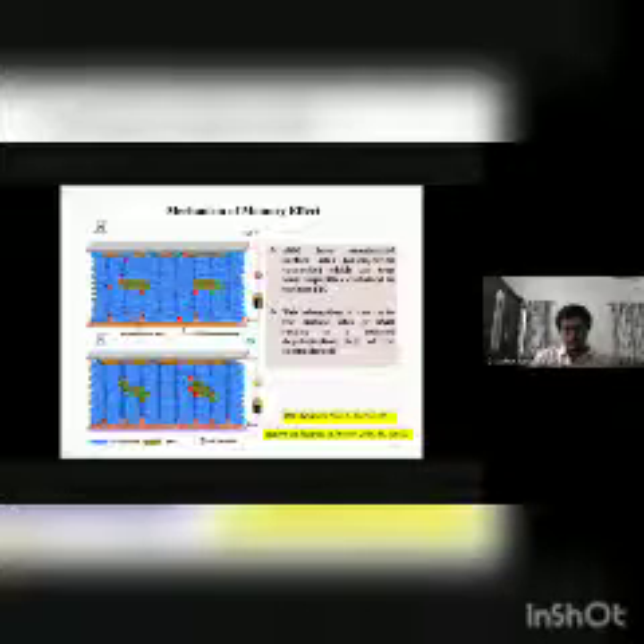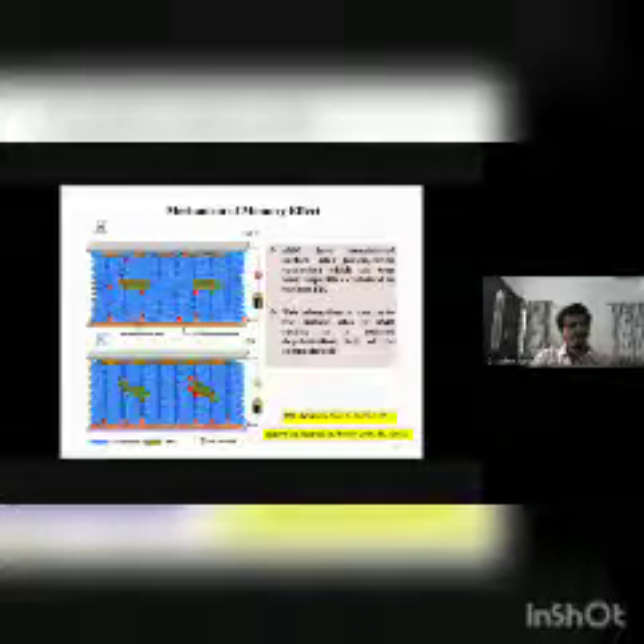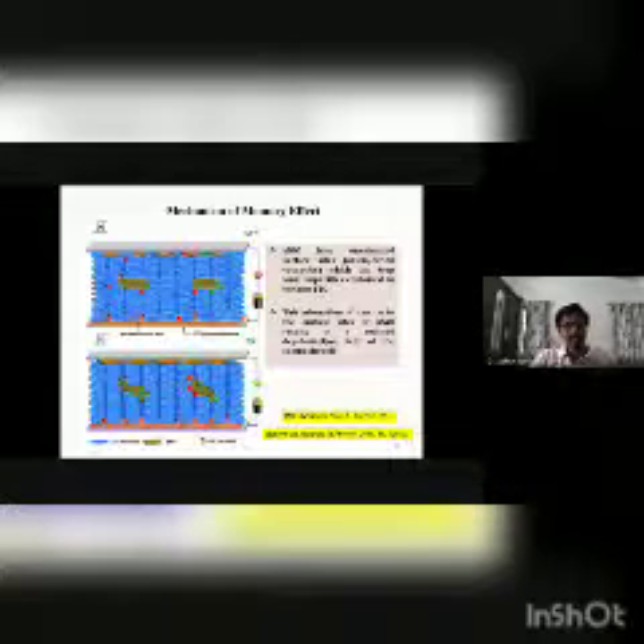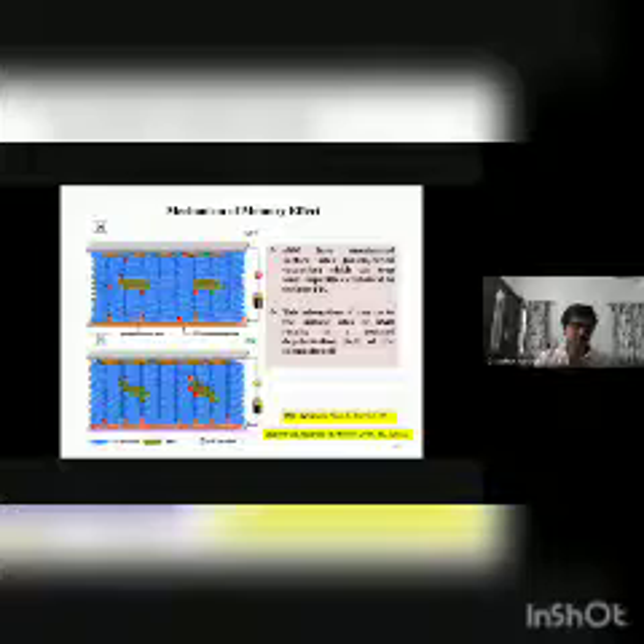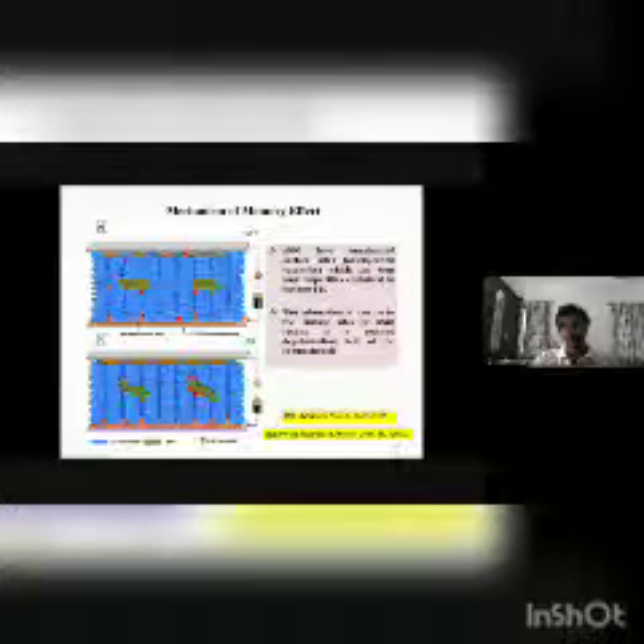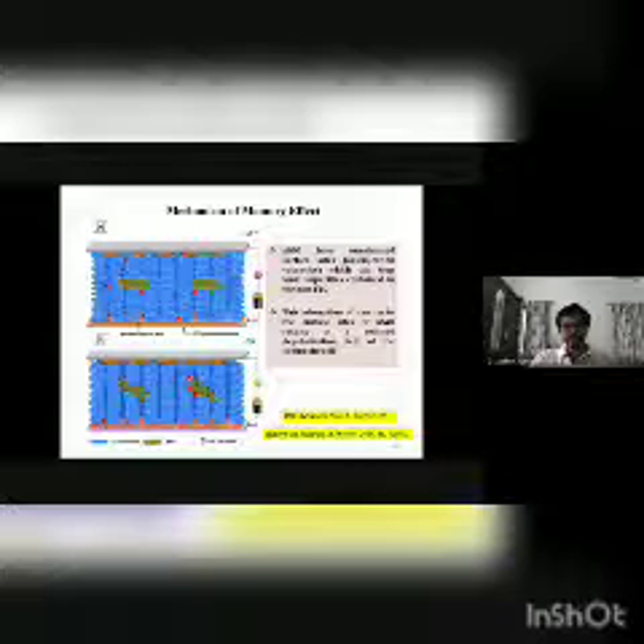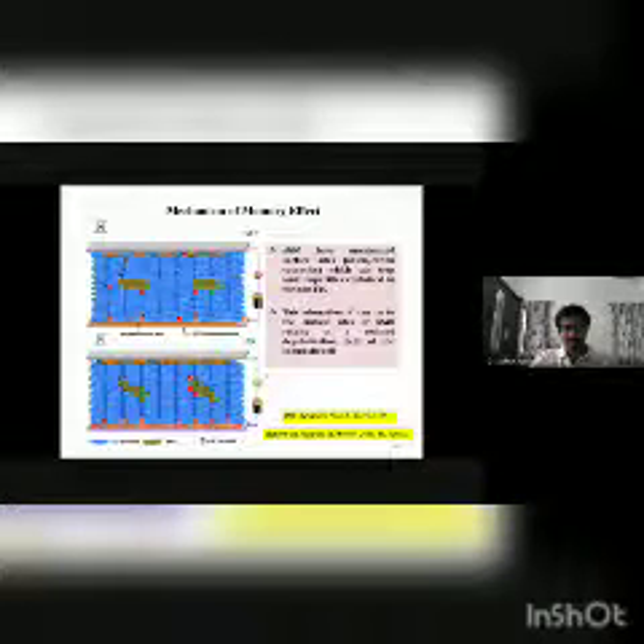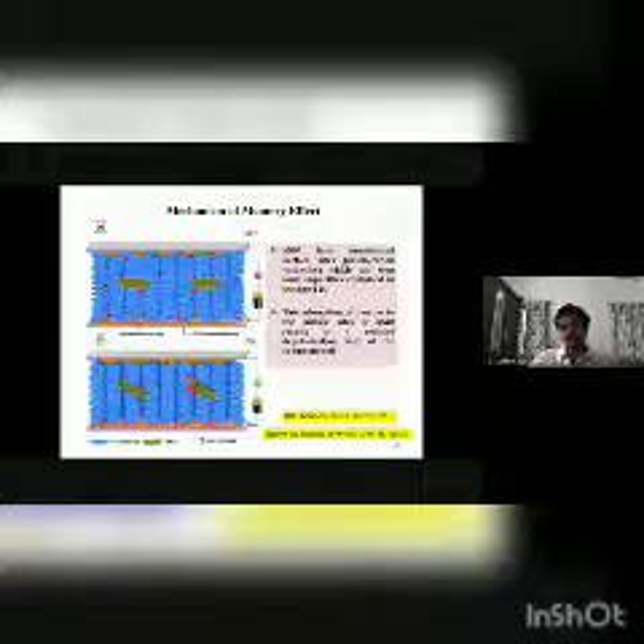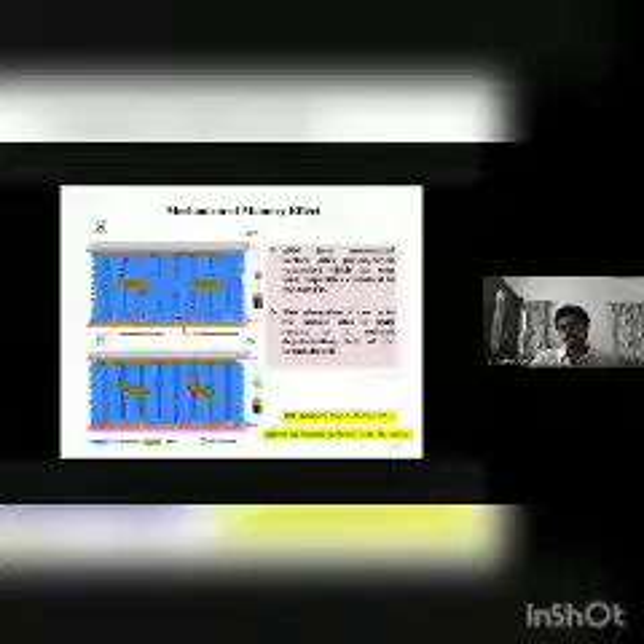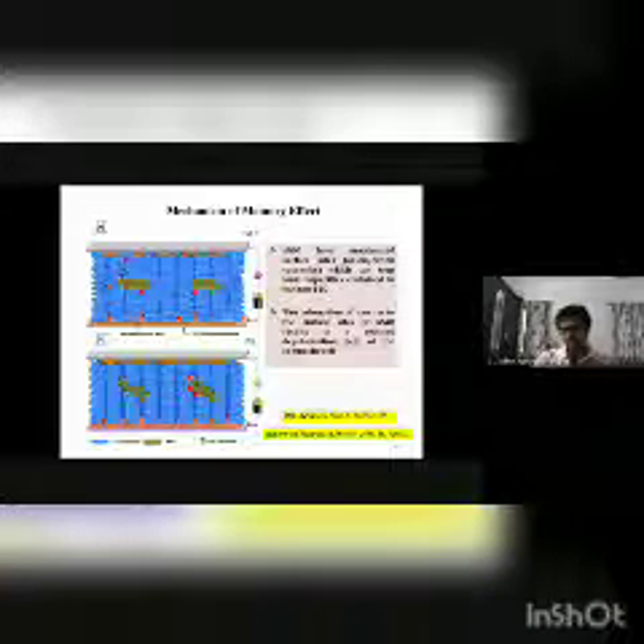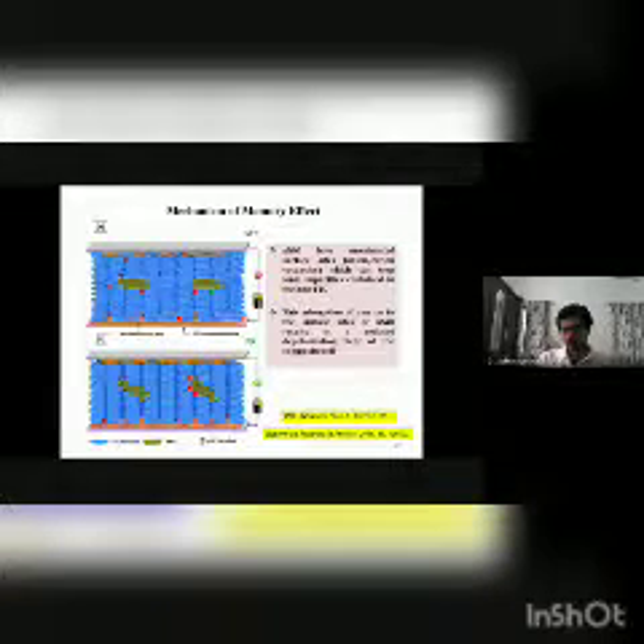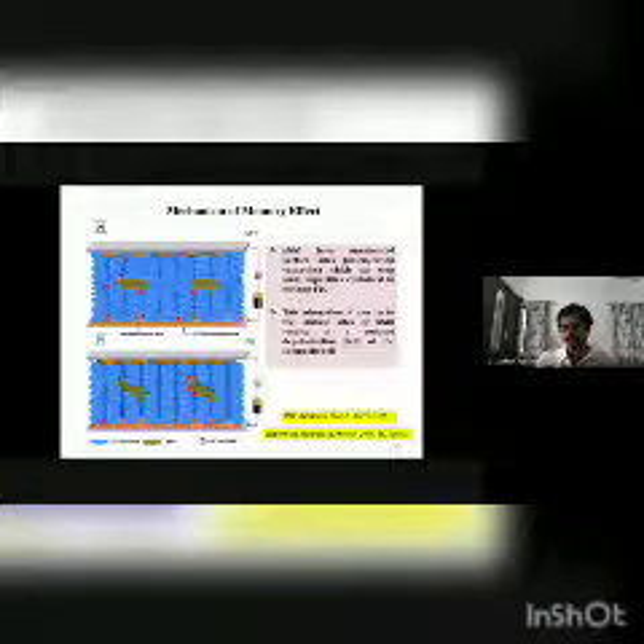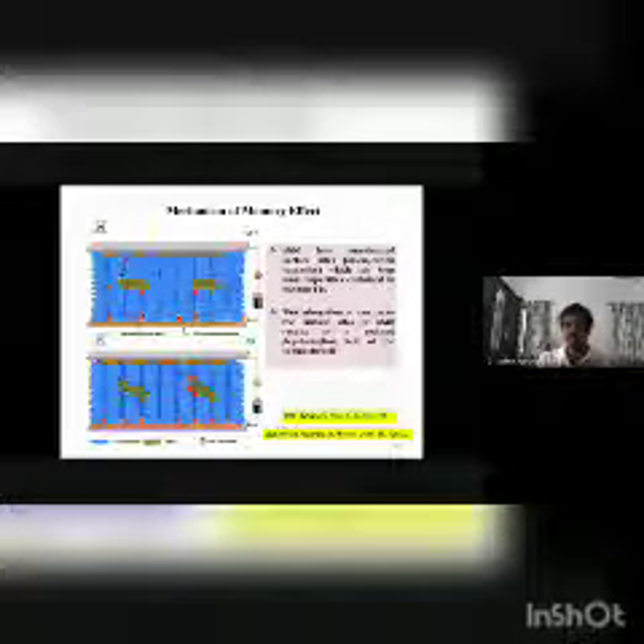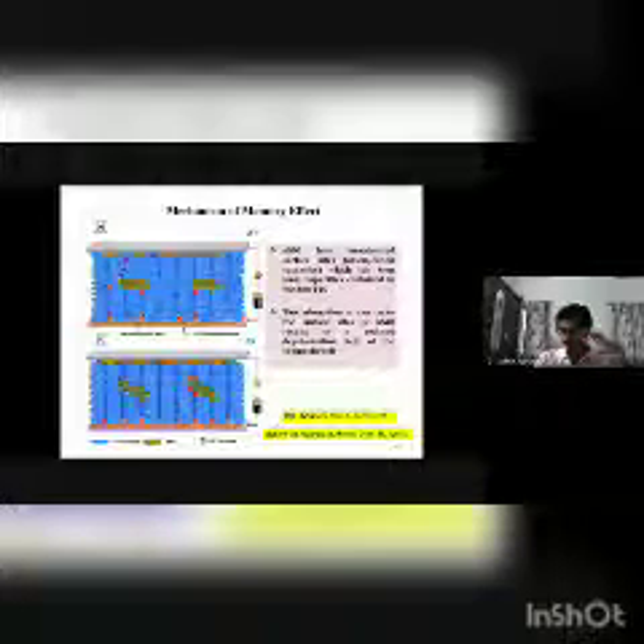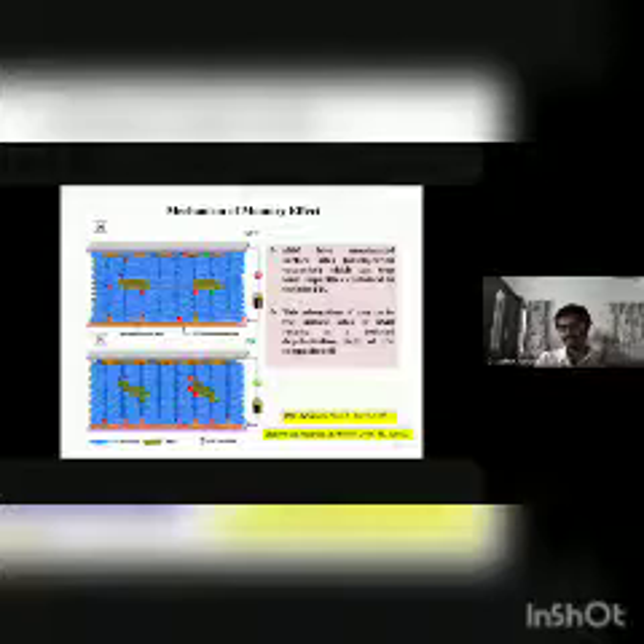Because of that, there will be an effective reduction in the depolarization field, and this depolarization field cannot revert these FLC molecules when the bias is removed. So because of this reduction in depolarization field, due to trapping of ions, there will effectively be a memory for these molecules. That means when the molecules are switched, there is no depolarization field when you remove the bias, so the molecule has a tendency to remain in that state for a particular duration. If the depolarization field were present, then the molecule would have to come back.